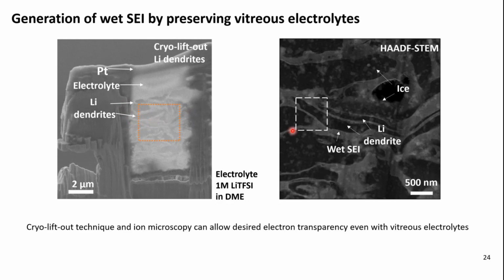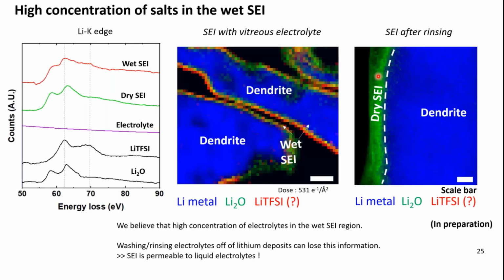And this shows how we transfer our sample to a cryo-TEM holder, and this shows a HRTEM image. The HRTEM imaging shows the lithium dendrites and vitrified electrolyte. And because SEI and the vitrified electrolytes are composed of similar constituents, we cannot easily tell where the SEI and vitrified electrolyte are through HRTEM imaging. However, when we use EELS, we can clearly see the existence of SEI at the edge of the lithium dendrite. We term the SEI with the vitrified electrolyte as wet SEI here.